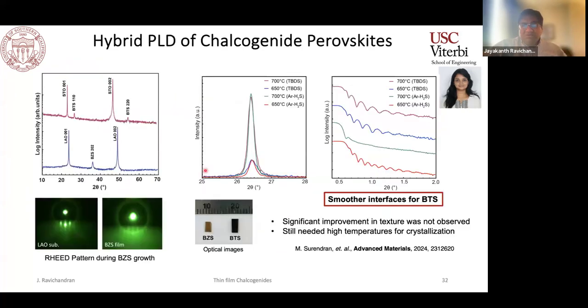Then we went back to solve some of the issues that are related to the growth of the chalcogenide perovskite, which motivated a lot of our work here. And even in this case, after we resorted to the hybrid PLD technique, the texture was not significantly better than what we started with in the case of our argon H2S. But nevertheless, we wanted to go back and check whether there is anything intrinsic to the material itself that limits our growth, or is it related to how well our processing conditions work.